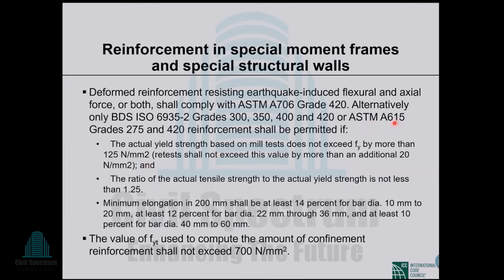Now, you can use ASTM A615 grades 420 or 275 or BDS ISO these standards if the actual yield strength based on mill test does not exceed Fy by more than 125 megapascal. It is always bad to have higher yield stress, as that reduces the ductility that we want for seismic design. So that's why it is restricting the value of Fy. Suppose our steel is BDS ISO 420, but I'm getting yield stress very close to 500. So is that okay? There is an upper limit.